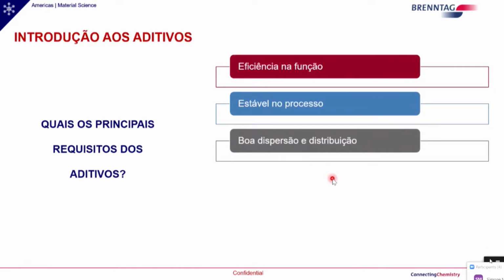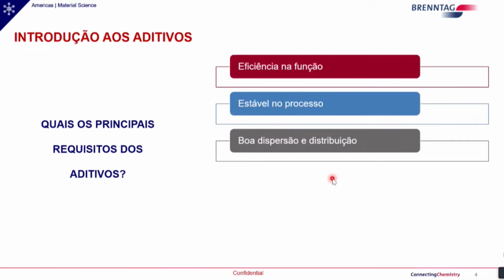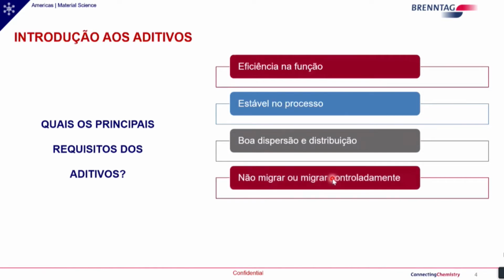The material must have a good dispersion and distribution rate. So we believe in a polypropylene compound used with talc, which is widely used in the automotive industry. So talc should be distributed throughout the part. And in order to make the additive effective, the additive should be well dispersed, well distributed as well. So that's one of the challenges when it comes to additives.